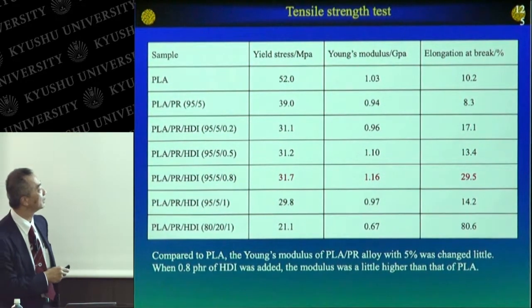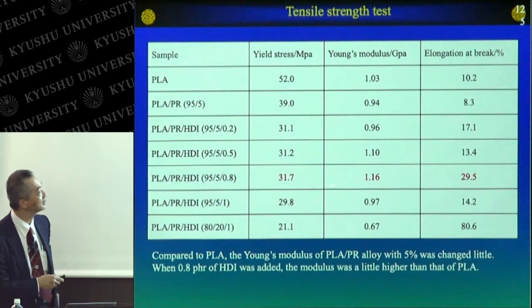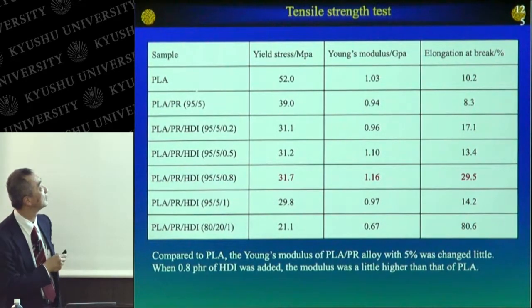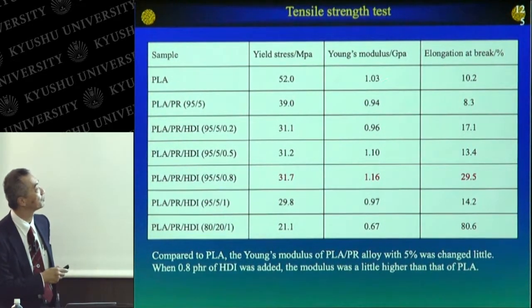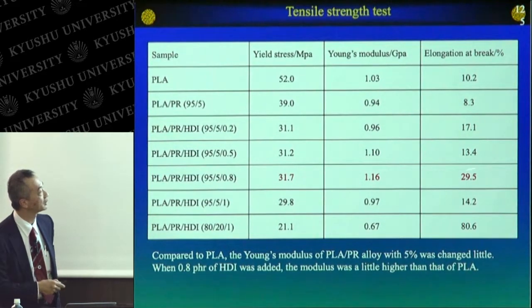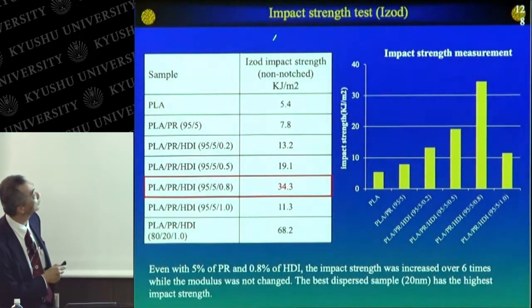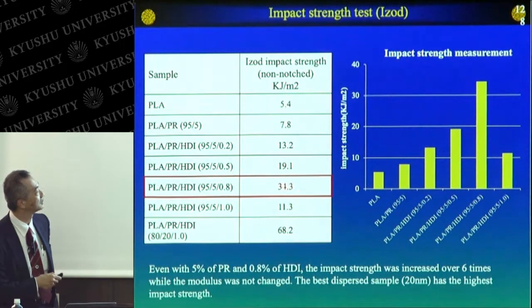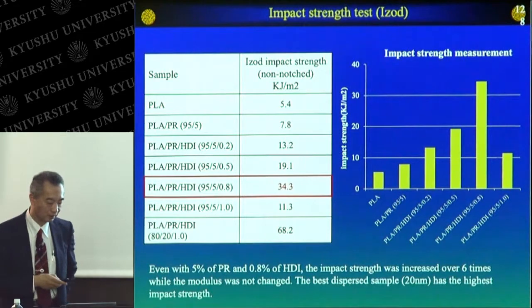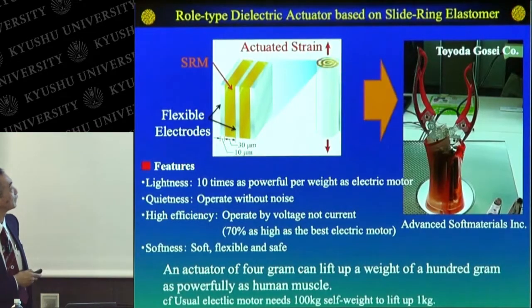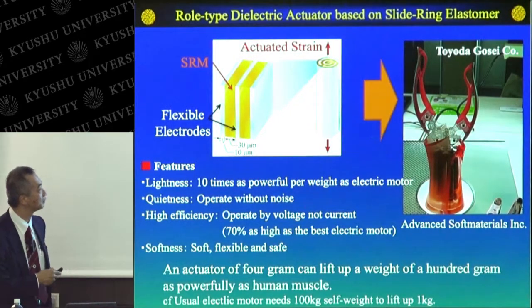So when we add only 5% of polyrotaxane to the polylactic acid, the Young's modulus is almost the same as polylactic acid without polyrotaxane, but the elongation at break is improved about 3 times. And this shows the impact strength test. You can see the impact strength is improved about 7 times compared to the neat polylactic acid.